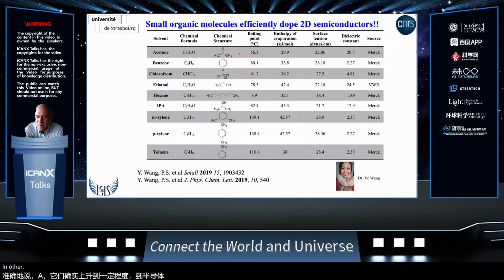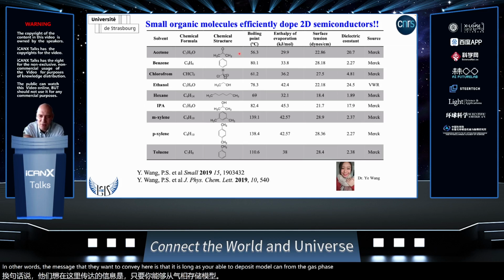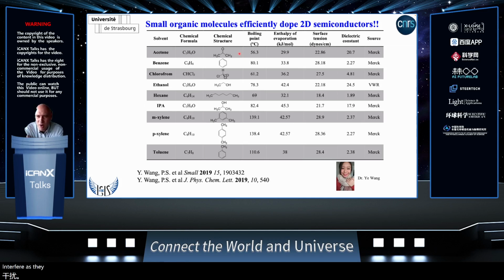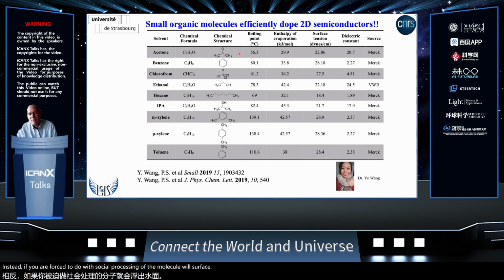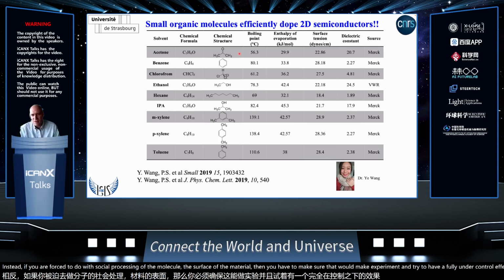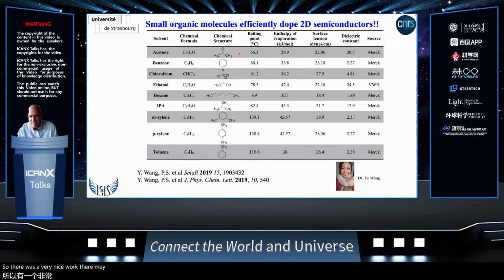So in other words, the message that I want to convey here is that as long as you are able to deposit the molecule from a gas phase, that's the best way to do it, because then you can forget about any potential interference of the solvent molecule. Instead, if you are forced to do solution processing of the molecule on the surface of the 2D material, then you have to make sure that you do a blank experiment and have fully under control the effect of the solvent molecule alone. That was a very nice work done by Ye Wang that we reported in 2 separate papers a couple of years ago.